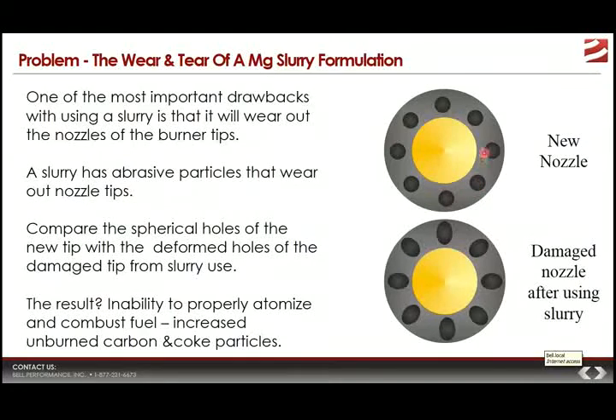This is an oil gun and it's got a nozzle with these spherical holes. This is the way it's supposed to look. But when you start adding insoluble magnesium oxide and running it through this, those abrasive little particles actually change the shape of the nozzle holes over time. This is not going to deliver the fuel into the combustion area with the same efficiency as this. And that is a problem that users have to contend with if you're using a magnesium oxide, a MagOx slurry.